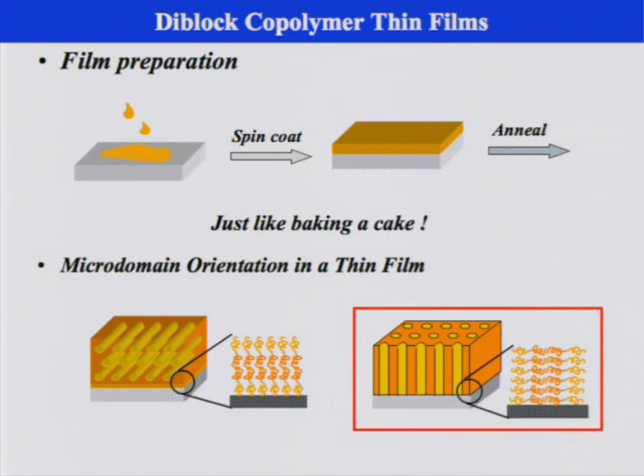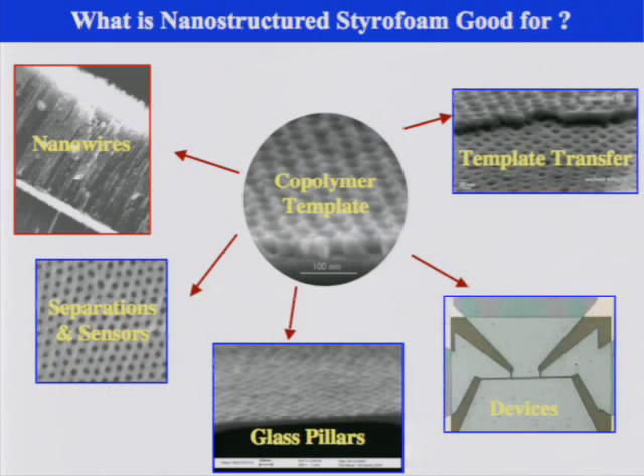In the case when you have cylinders standing normal to the surface, polymethyl methacrylate can actually be used as a photoresist. So if you shine UV light on it, I can chop it up and then the substrate gets selected and removed. What you're going to get is styrofoam, but in this case, it's nanostructured styrofoam film.